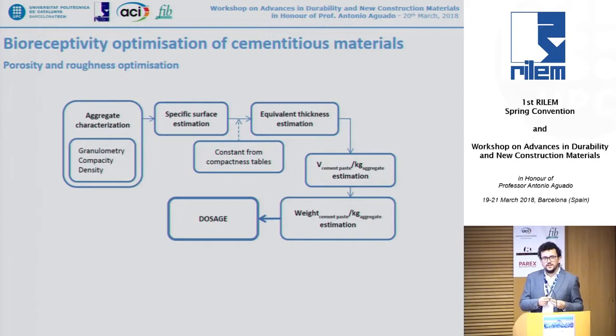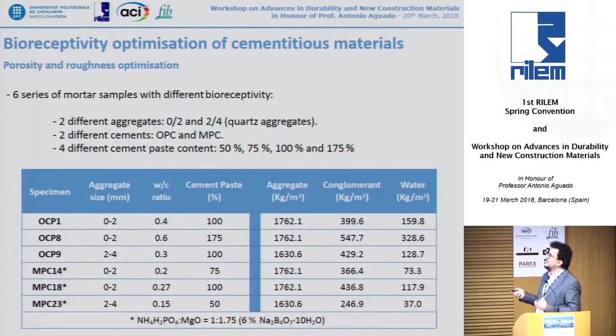But there is not only the reduction of the pH of the material to allow the biological colonization; we also need to have an adequate porosity and adequate roughness in order to allow these living organisms to colonize the surface. So we made an approach in order to obtain a controlled porosity material with a large porosity, so that we can have enough water inside of our material to promote the biological growth, but also a very good roughness for the organisms to colonize the surface. Following this approach, in order to estimate the amount of cement paste that we need to have this porosity in our material, we obtained the dosages that we are actually using, and we evaluated this bunch of mixes in order to determine the roughness and the bioreceptivity of these materials.